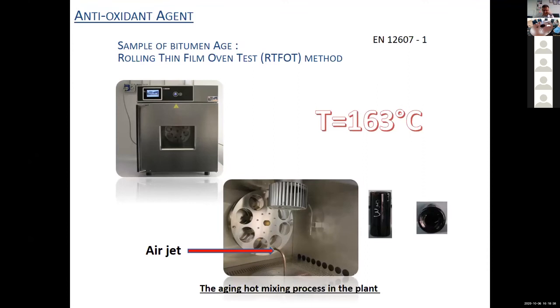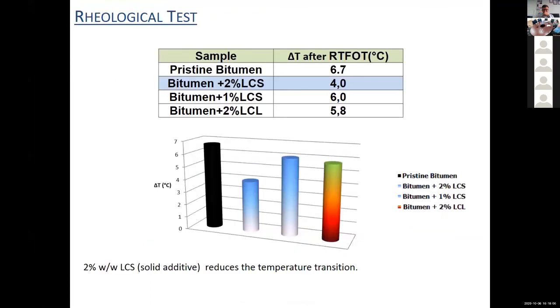Each modified bitumen plus a reference binder free of additives was divided in 2 aliquots, of which only one was subjected to the process of artificial aging. To evaluate the effectiveness of antioxidant agents, the rheological measurements were performed before and after aging. In general, a good antioxidant agent should not change the viscosity property and the transition temperature after the aging process.